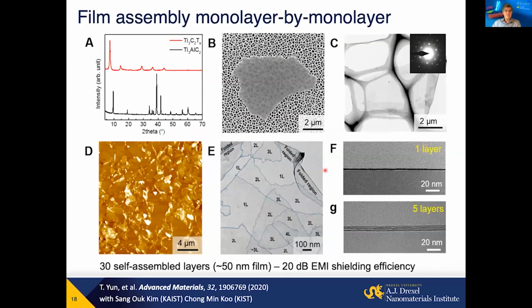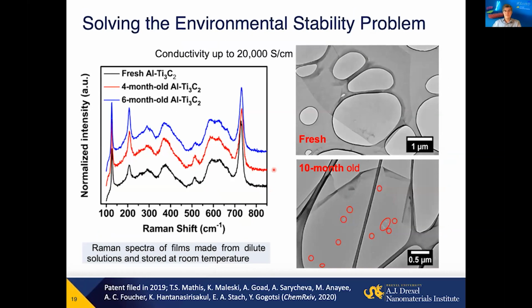That's very important because it's easy to produce films. We don't know yet how to make wafer scale films of single crystal MXene by CVD. By assembling flakes into monolayer films with just overlapping flakes, it's possible to make pseudo monolayer films. And this work was actually done together with Sang Ouk Kim and Chong Min Koo, two Korean collaborators. And then it's possible to pile up layer after layer and study the effect of the number of layers on properties of this material. Also, in earlier studies, it was shown that MXenes can oxidize in air.